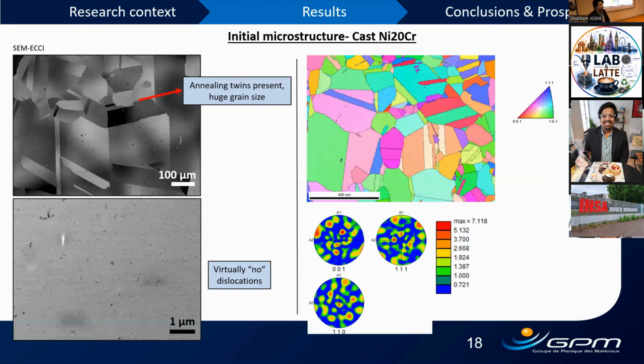To have a good understanding of how LPBF microstructure changes, it is important to have a look at how the cast or traditional alloy looks after recrystallization. This is recrystallized nickel 20 chromium. We see annealing twins and huge grain size, which can also be seen in the grain orientation map, with a maximum intensity of 7.1.